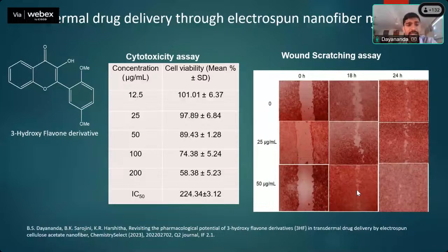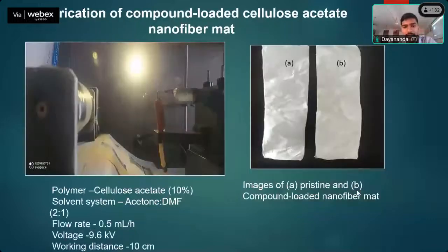So that is why it was decided to load into the nanofiber mat, intended for use as a material. Cellulose acetate was taken as the polymer, with acetone and DMF as the solvent system. The flow rate was fixed at 0.5 ml per hour, voltage was fixed at 9.6 kilovolt, and the working distance at 10 centimeters.